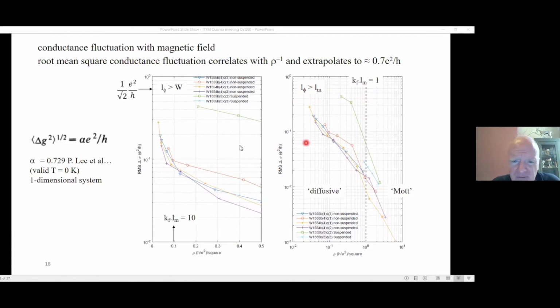which is interesting. If I replot that data in the metallic regime, so I've plotted this now on a linear scale, I wanted to extrapolate to 0 resistance, to infinite conductance. What do we get at 0 resistance? Now, I haven't put any fits on here because I don't believe there's a theory that relates resistivity to root mean square conductance fluctuation. But with a bit of imagination, you can imagine they're coming towards 1 over root 2 e squared upon h. And that's exactly what was predicted by Patrick Lee back in the 80s for this behavior, that the root mean square conductance is approximately alpha e squared upon h.